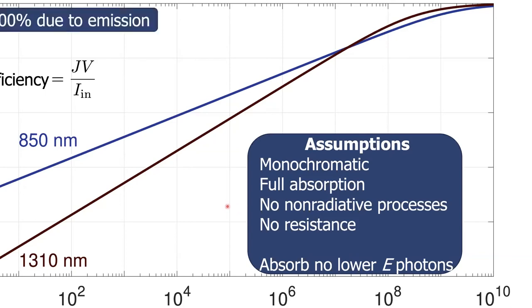And the answer is that our device not only absorbs photons, but it also has to emit them. This is the same thing as Einstein's A and B coefficients, only in a solid state context. If we absorb light, time reversal symmetry for our material says we're going to have to emit it. Some of those emitted photons will leave. That's a loss process. As we have higher intensity, we can approach 100% efficiency. But we cannot do it at lower intensity light.